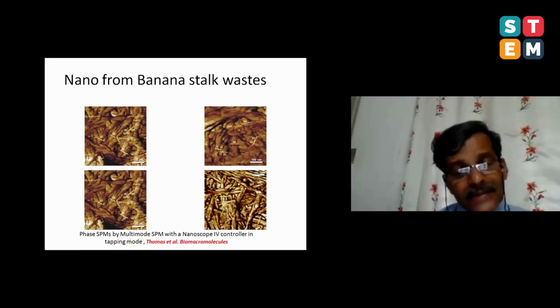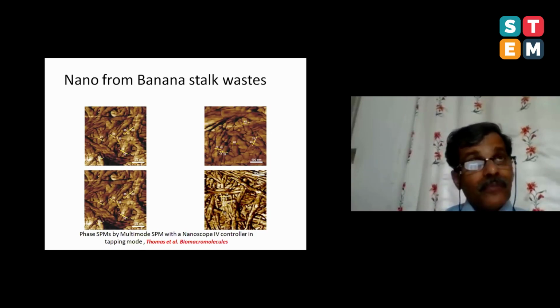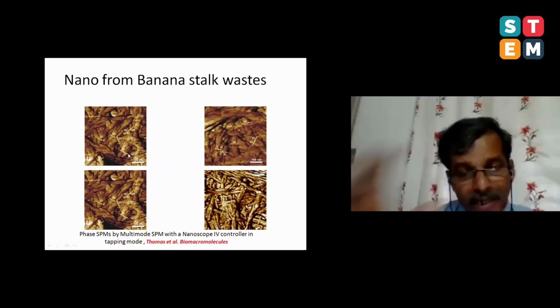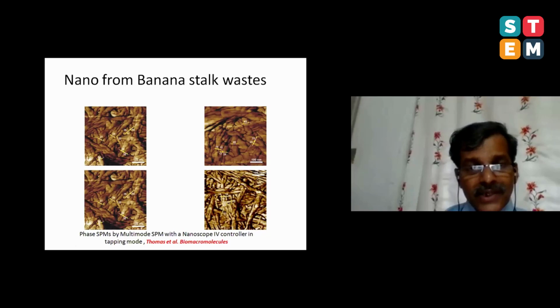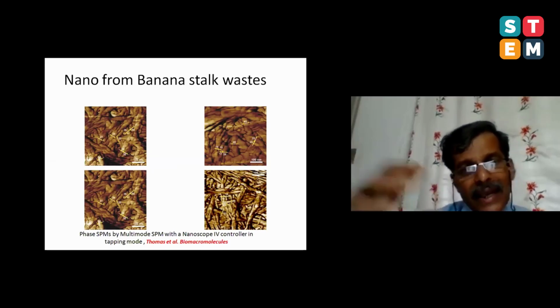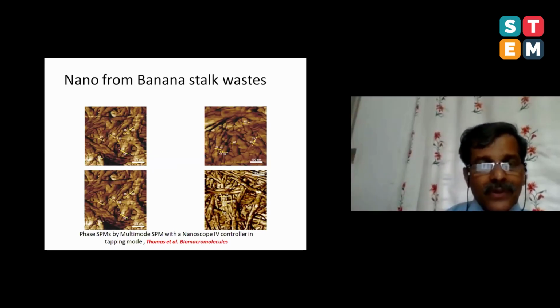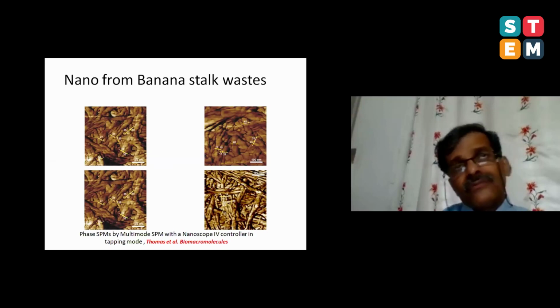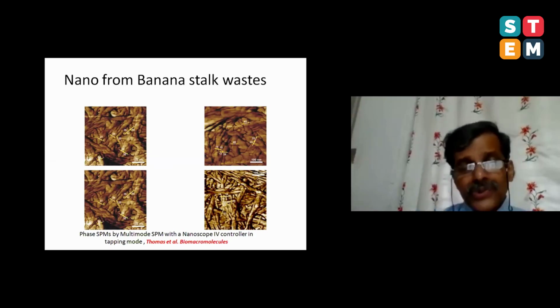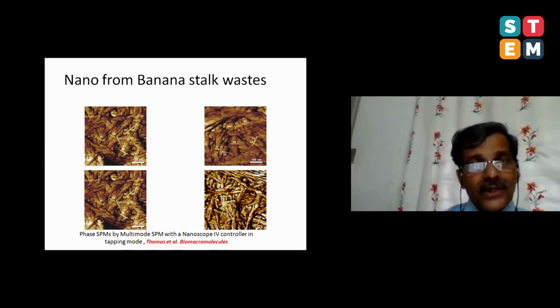I will show you some nice diagram pictures of nanomaterials we have made from banana waste, the stalk of banana. The stalk of banana has been subjected to acid hydrolysis. And look at this, we have made nanocrystals of something like 100, 200 nanometer length. And the diameter is in the range of maybe 50 nanometer, 35 nanometer, 27 nanometers. We have a distribution of sizes, distribution of length and distribution of diameter.